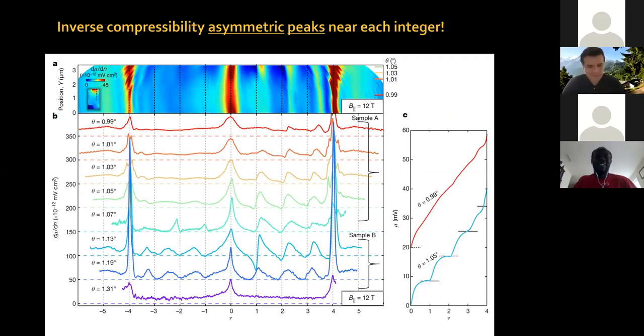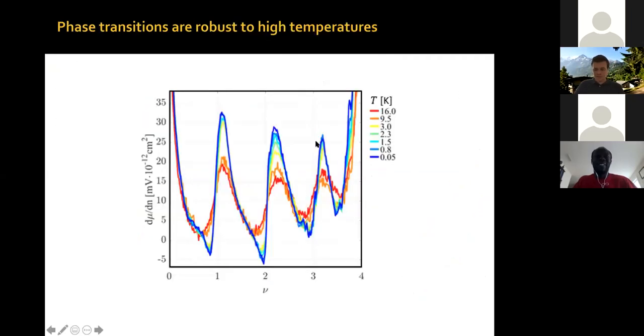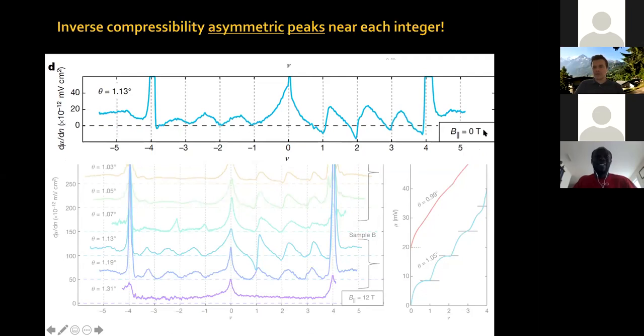Sample B is actually a much better device that this time we characterized at MIT, and we made sure it was a good device in order to ship to Weizmann, okay? And the phenomenology and the data are much richer, and it has much more uniform regions, large regions with uniform twist angle, okay? Where our colleagues at Weizmann can take detailed measurements. So in that sample B, all of this phenomenology is present even at 0 Tesla, okay? You can see all of these asymmetric sawtooth peaks, okay?